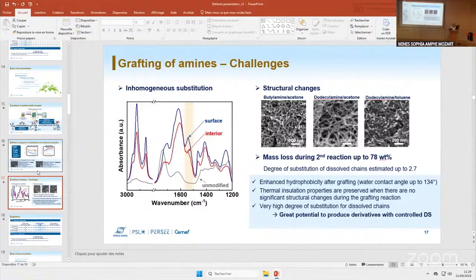Maybe by performing a very mild impregnation with the CDI first before heating, because once you start heating, the reaction will start, and you will be consuming CDI at the same rate as, or simultaneously as, it keeps diffusing into the gel. So I think a mild impregnation at room temperature before you get the reaction started by heating. I think it would be great if we had time, doing the reaction at low temperature is a very great alternative. I fully agree. We realized it a bit late. You have done an impressive amount of work on that topic anyway, so this is just a detail.